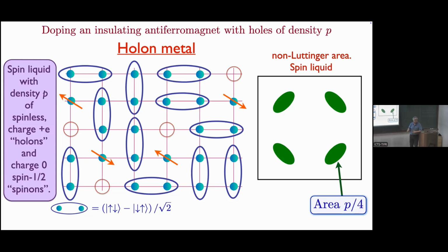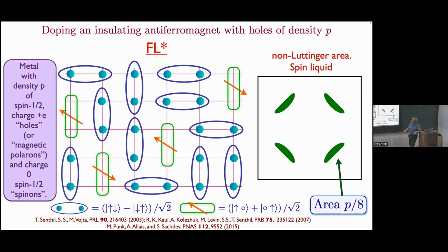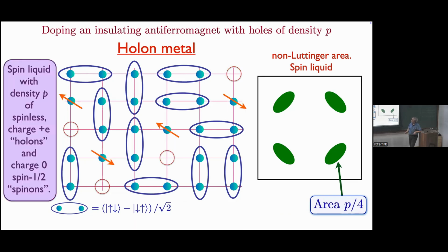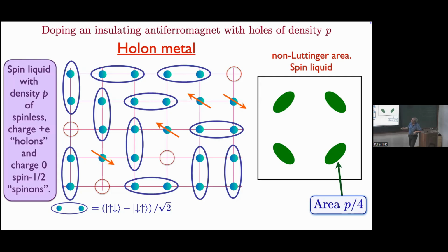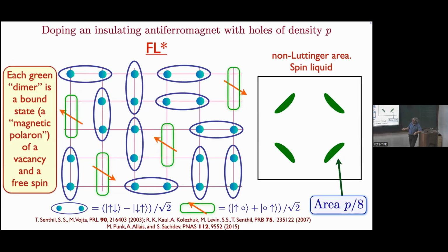I think in Kivelson's model, with the dimer model, these were fermions, spinless fermions. So this is just a fluctuating antiferromagnet. The difference from the thermally fluctuating antiferromagnet that Pines, Chubukov and Schmalian studied is that they're mostly thermal fluctuations. Here you have quantum fluctuations leading to fractionalization, and that gives you the holon metal. Now for the FL*, you can ask why would the bound states form? Well, the point is that to create the spinons, it costs you energy J, because the spinons are fractionalized from the valence bonds, and you break them apart. But the binding energy of a spinon and a holon is t.